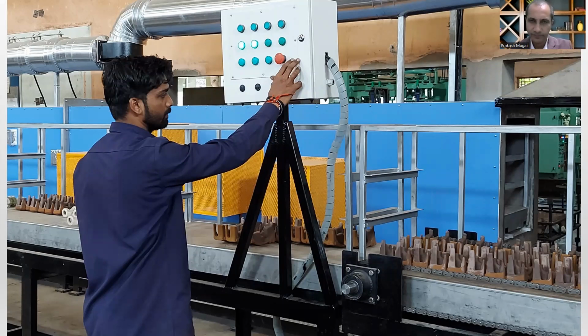So core becomes hotter in nature? Yes. They do become hot, but they don't become very hot like in a conventional oven. What is the surface temperature approximately? Typically, if you see the surface temperature, it would be around 95, 100, between that range. Okay. So it is one of the tests we can say for checking whether our cores are dried properly or not by using an infrared gun. Yes, you can use that.